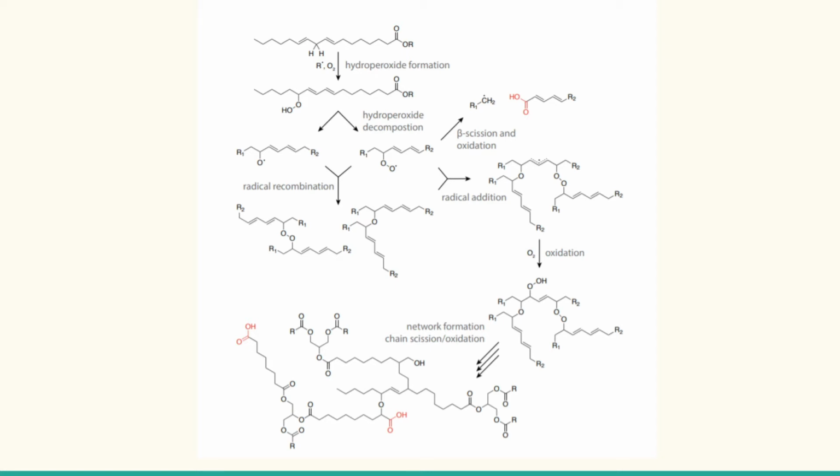The resulting product then undergoes a reaction with molecular oxygen to form a hydroperoxide species containing conjugated carbon double bonds. Upon decomposition, the hydroperoxide can form a number of molecules, including hydroxyl and hydroperoxyl groups, ketones, and peroxyl. Ether cross-links between fatty acid chains are also produced. Furthermore, beta scission and oxidation of the hydroperoxide products can form carboxylic acids and aldehydes.